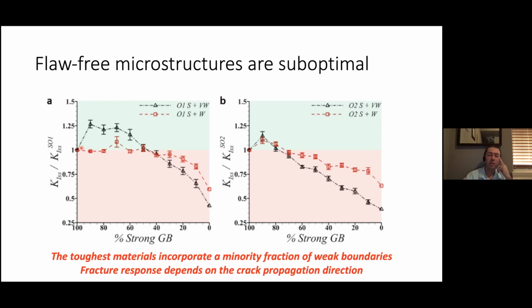And then we also looked at another type of grain boundary which we call very weak, which is basically a weak grain boundary that has even lower intrinsic toughness, and that's the black curve up here. And so, as you can see, there is this admixture of weak grain boundaries that you can put in here that actually toughens the material. And moreover, when you take that admixture of weak grain boundaries and you make them weaker, this toughening effect becomes more pronounced, right? So the weaker you make the boundaries, the tougher the overall composite becomes.